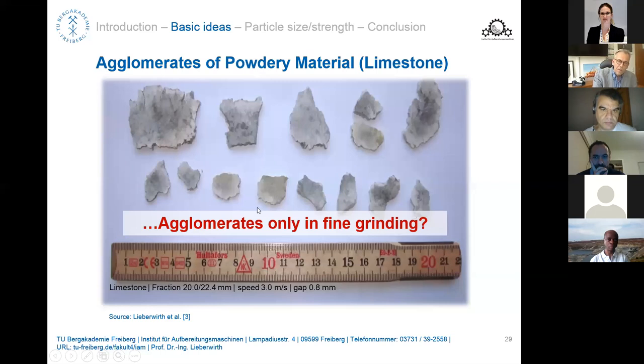Let's stop this one here and jump back to the other presentation again. We produced these flakes here with a limestone fraction of 20 millimeters, at a surface speed of 3 meters per second and a gap of 0.8 millimeters, which was pretty fine. The focus there was: what is the relationship with diameter, and is there any influence of the material? We also used other materials. Is there any influence of the material, how it is taken into the double roll crusher?